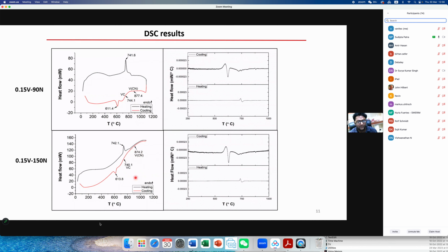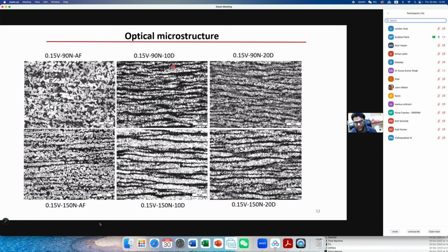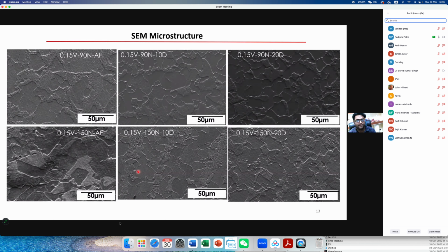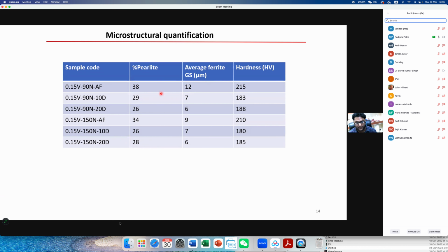So the optical microstructure of as-forged and the cooling rates of 10 degrees and 20 degrees centigrade, we observe a ferrite pearlite structure, almost recrystallized ferrite and pearlite, in both the cases, 90 and 150 nitrogen. Here apparently it looks like a little bit of refinement takes place, but when we measure the grain size and the pearlite fraction from the SEM and optical microscopy, we found that the ferrite grain size in 90N as-forged is 12 micrometer, and in case of 150 we are getting 9 micrometer.